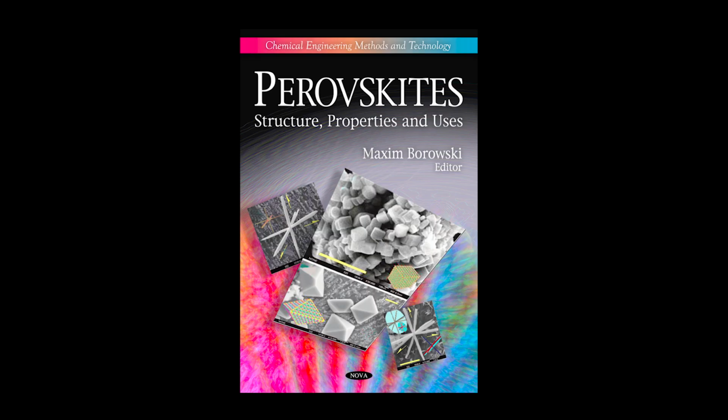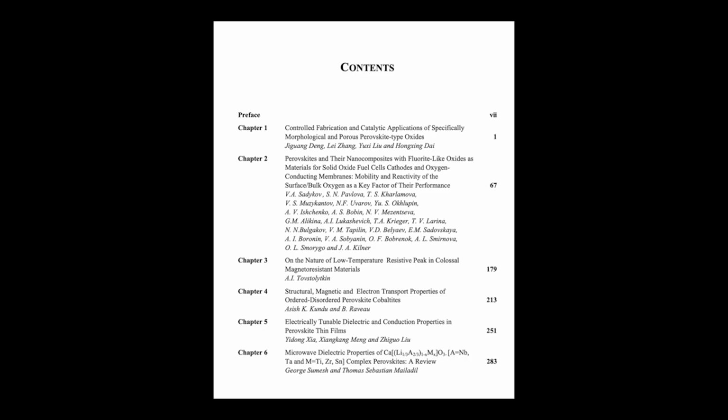Perovskites, though, offer a potential workaround, again through clever structural and chemical tuning. Certain alkali metal-doped perovskites, for instance barium stannate, BaSnO3, or cesium-doped lanthanum manganite, La0.8Cs0.2MnO3, show remarkable resistance to this carbonation problem. The key seems to be that the alkali metal dopant, like cesium, tends to segregate to specific surface sites, and its presence there actively inhibits the nucleation and growth of that stable carbonate phase. So instead of getting poisoned by forming carbonates, the surface remains available to form the desired active nitrate species for NOx storage. This allows these perovskite-based materials to maintain excellent NOx absorption capacity even when operating in realistic exhaust environments with high CO2 concentrations.